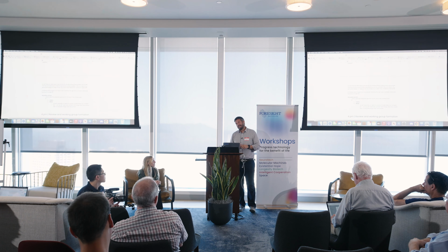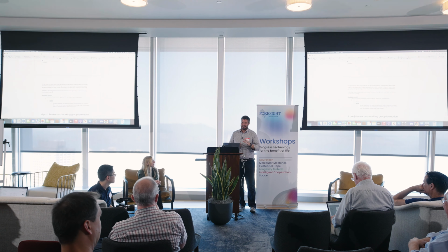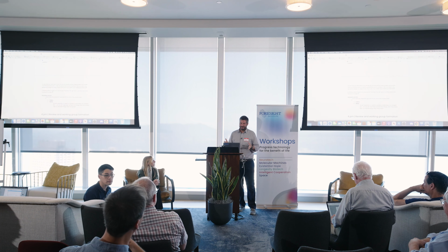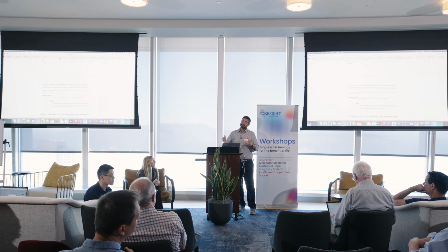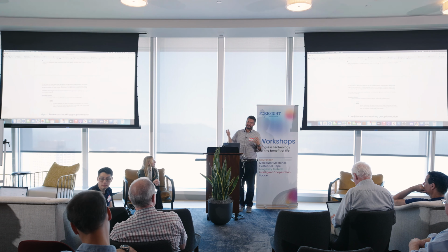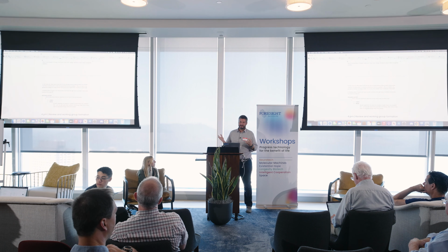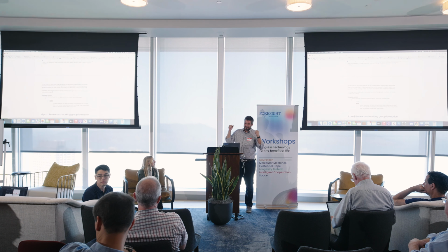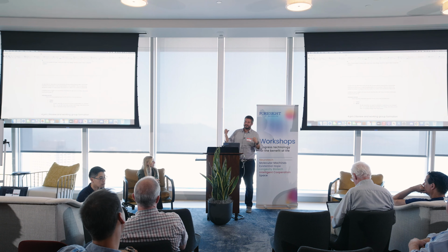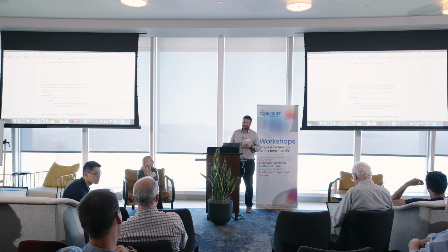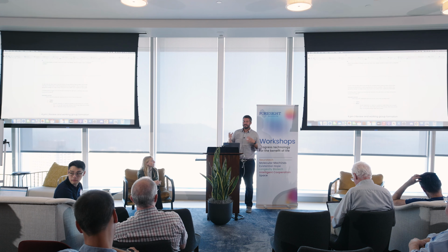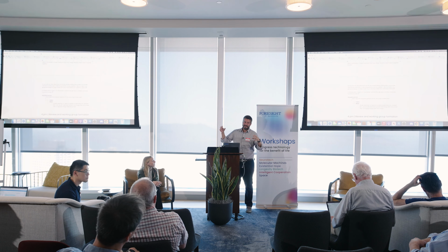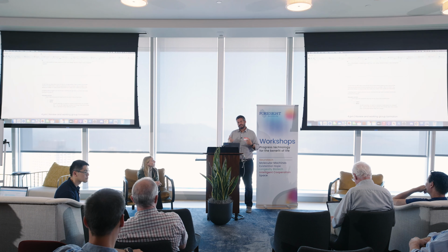It depends. Rigidity is a tricky word, and it's always a question of how rigid. But we can make things with persistence lengths of tens of microns, let's say 20 microns. So you can build very, very stiff things, but then it's always a balance, because we also want to build in dynamics so that we can reconfigure. I think that's the big challenge. You can make something very, very stiff over a 10 micron scale, but having something that is reconfigurable and stiff is a challenge.